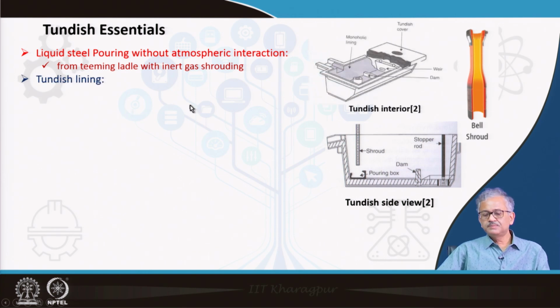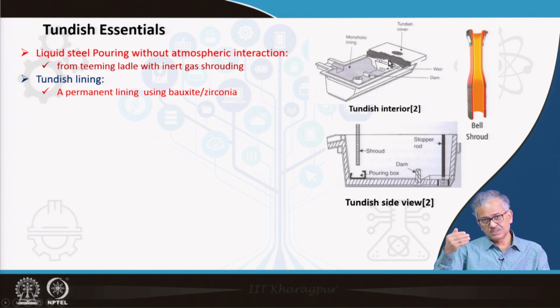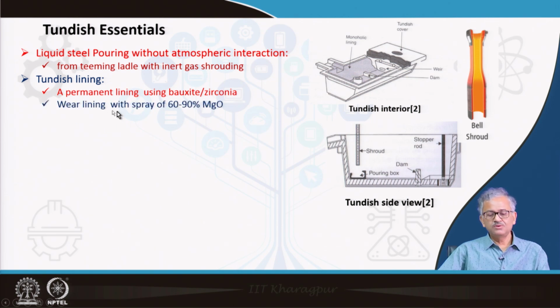Tundish lining: you can find there is a monolith lining. A permanent lining using bauxite or zirconia is there, just after the steel shell. Then you have a wear lining over it. You can find a monolith wear lining, not brick, but a ramming material. It is basically a spray of 60 to 90% MgO, which is just sprayed. So it is a very MgO-rich monolith layer you can produce by spraying.